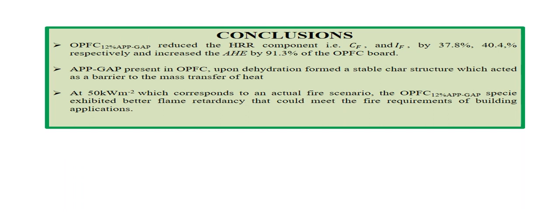In conclusion, the flame retardant added to the oil palm fiber reinforced polymer composite reduced the heat release component, that is, the contribution to sustain fire and the intensity of fire, by 37.8% and 40.4% respectively, and increased the available heat energy by 91.3% on the OPFC board. The flame retardants present in the oil palm fiber composite upon dehydration formed a stable char structure which acted as a barrier to the mass transfer of heat.